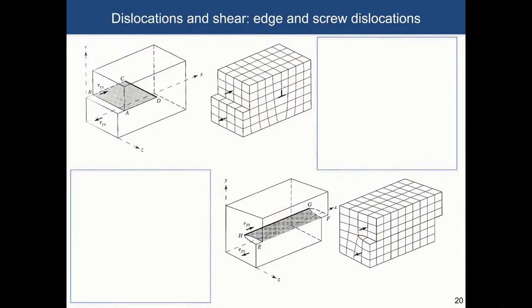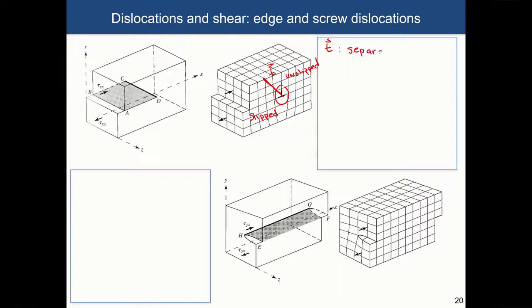To describe how they are formed, we need to define a slipped and unslipped part of the crystal. If you form a defect here, this is the slipped part of the material — the part of the crystal that slipped from its original position inside the perfect crystal. To the right of this defect would be unslipped. The dislocation line, or tangent vector, simply separates the slipped and unslipped parts of the crystal.